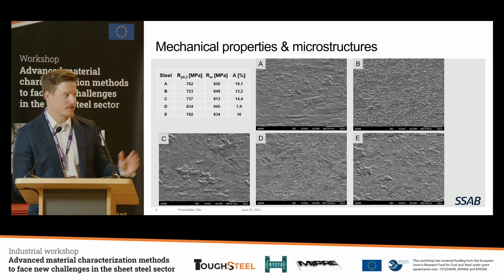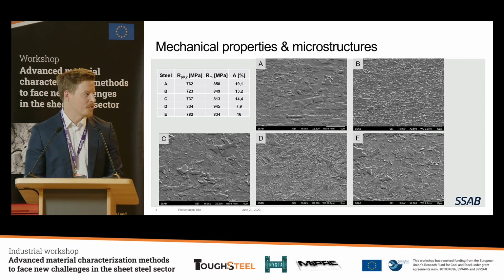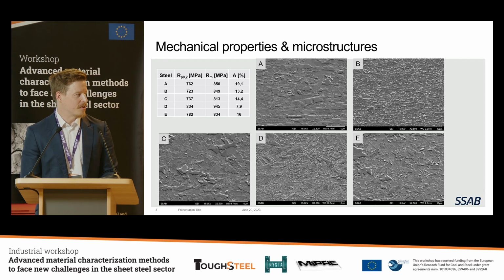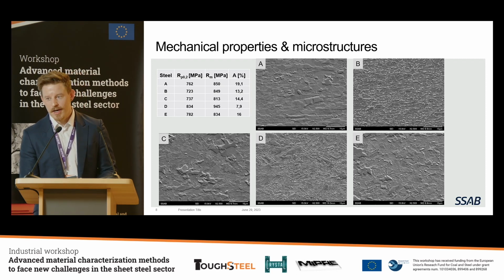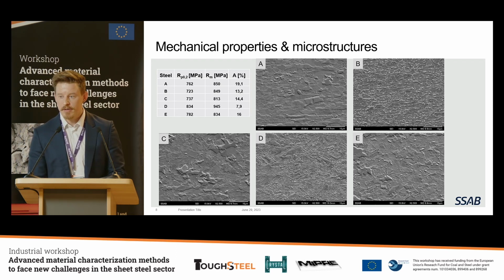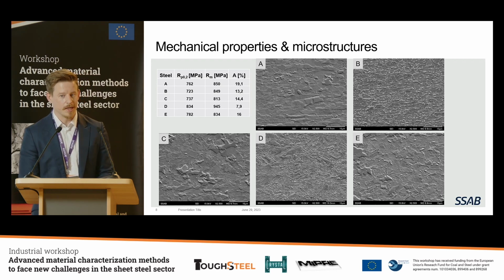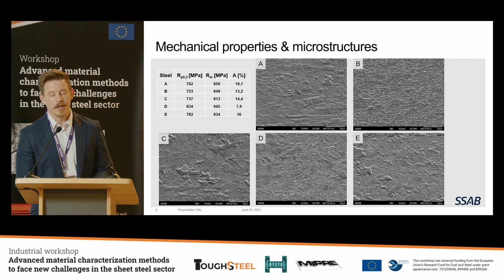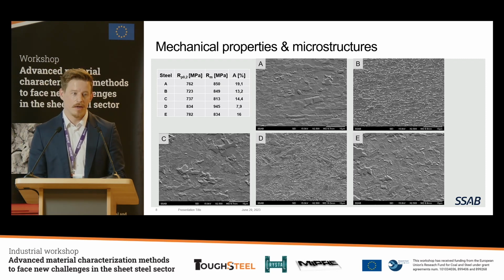I'm not even trying to tell what you are going to see there, because there is almost everything, starting from ferrite, bainite, quasi-polygonal ferrite, martensite, everything. So it's a really complex phase steel. And steel E, again, based on ferritic microstructure, again, a little bit different morphology there, but we could say that A, C, and E are ferritic steels, and B and D, those are clearly complex phase steels.